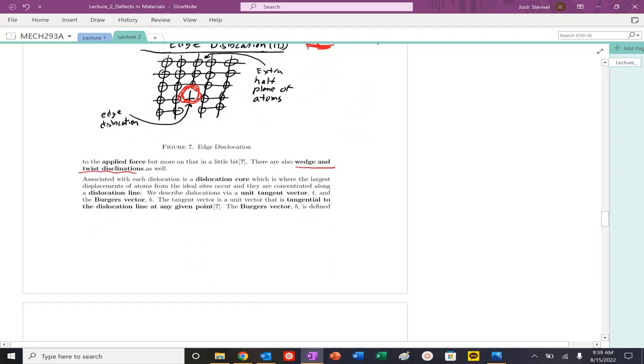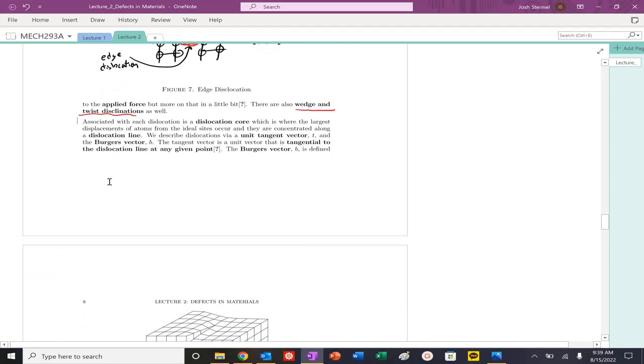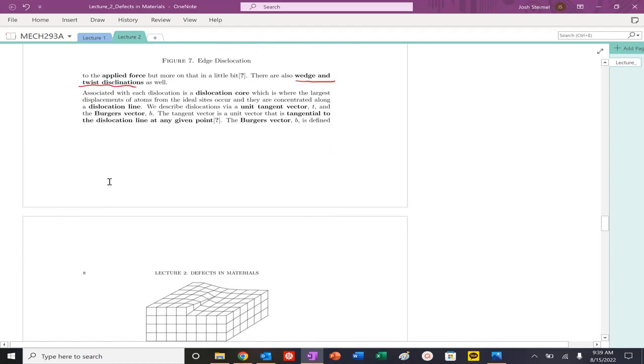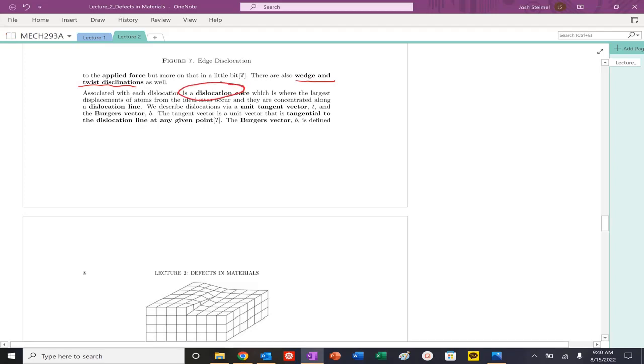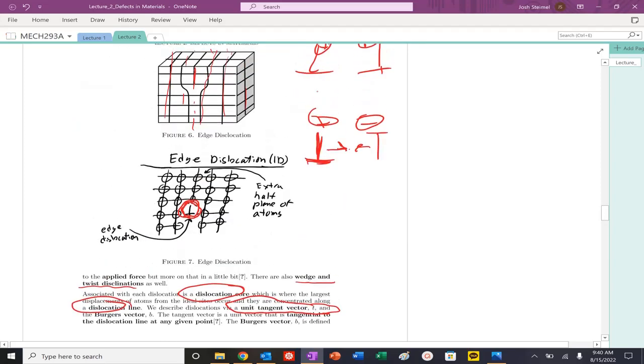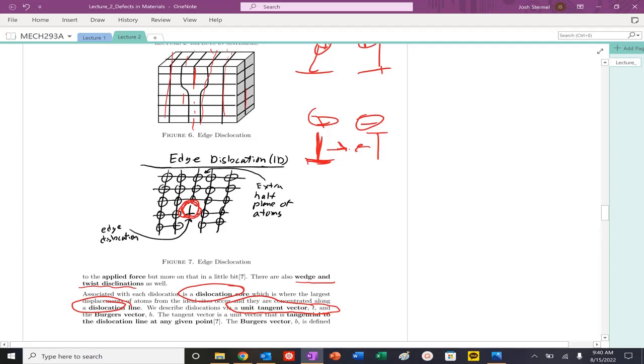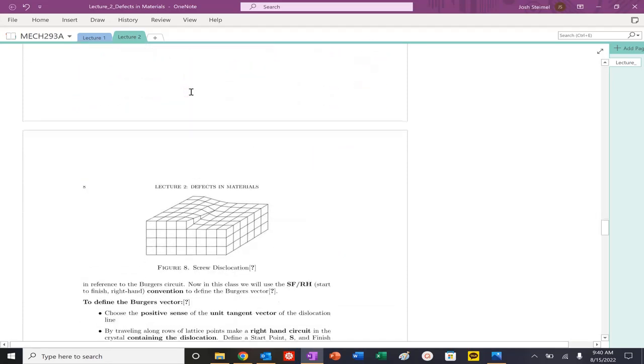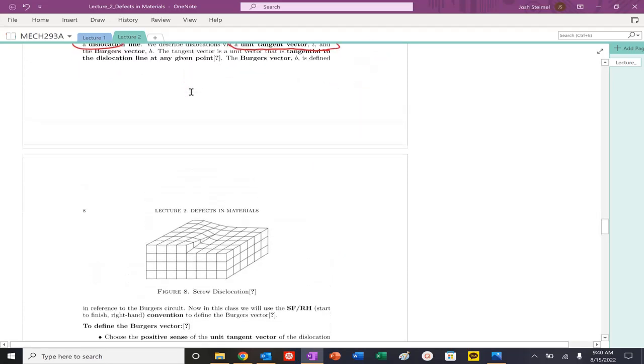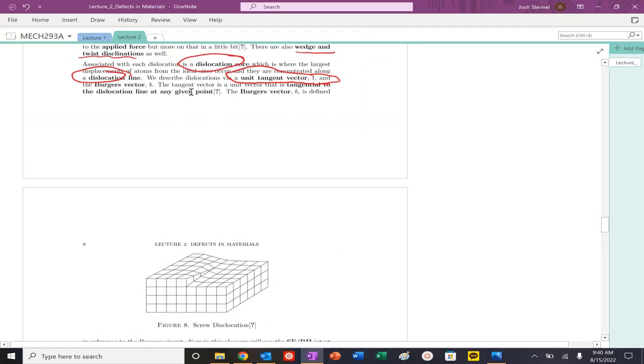How do we know if a defect is an edge dislocation, a screw, a right-hand screw, or a left-hand screw? It's all about how we can describe these defects. When we have a dislocation, we have a dislocation core and a dislocation line. We describe dislocations specifically with a tangent vector. A tangent vector goes along, it's tangent to that defect. My tangent vector is basically going, this extra half plane is going either into the board or out of the board, but it will be tangent to that dislocation line.